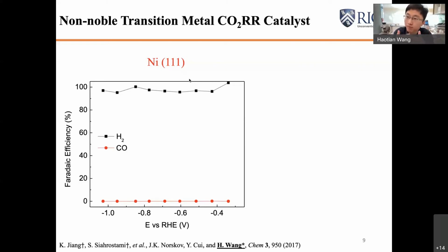And the second problem is, even though you can reduce some of the CO2 to become a CO molecule on the surface, as we generally know, those transition metals can be easily poisoned by CO, like human beings. If we breathe CO into our blood, the iron species in our blood can bind CO strongly and oxygen cannot exchange, right? This is the same thing happening on the surface of the catalyst.